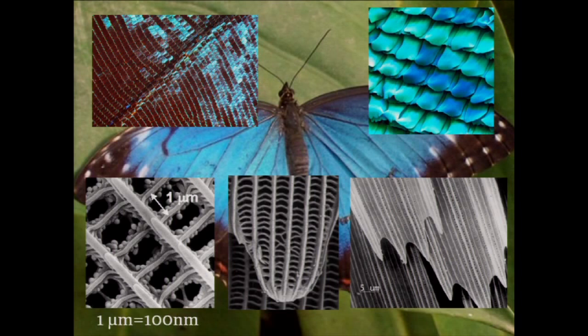You'll start to see, again, a deeply sub-wavelength, so kind of a smaller than the wavelength of light periodicity of the structure. So we've got both the wavelength scale periodicity, about 1 micron, and then we also have smaller scatterers inside that are about 10 nanometers. So it's this periodicity of transparent materials that gives rise to the very vivid colors that you'll see in butterfly wings.